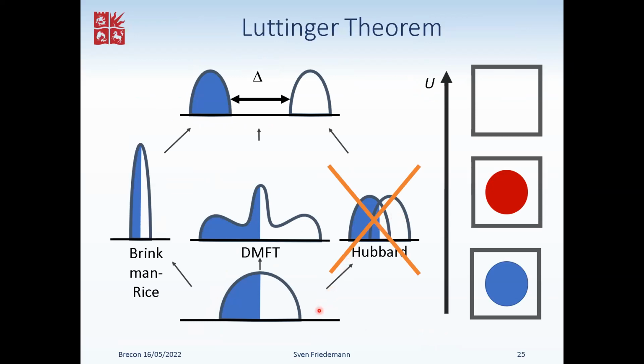The argument being that if you think about the half-filled non-correlated band, there are different ways to think of how we form a Mott insulator with the two split bands. In particular, both the Brinkman-Rice and the DMFT pictures tell us that we expect a peak in the density of states, but preserve the Fermi surface volume.